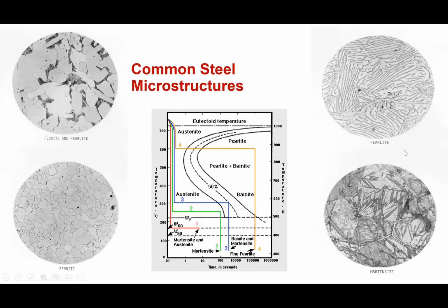So, some of the common steel microstructures, here's the one I was thinking of that had the pads. If we cool things very quickly, like path number 1, again this is temperature and time, you end up with martensite, which is over here in the lower right-hand corner. And this is all the same material, the same steel with the same elements in it. If you do path number 2, they don't show path number 2, I probably stole the graphic from another place. But if you take path number 4, for example, it looks like this, ferrite plus pearlite in the upper left-hand corner. And this is what we'll probably try to achieve most of the time when we have an A36, a nice balance.